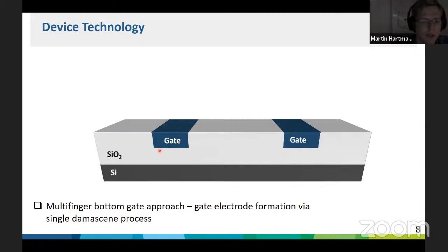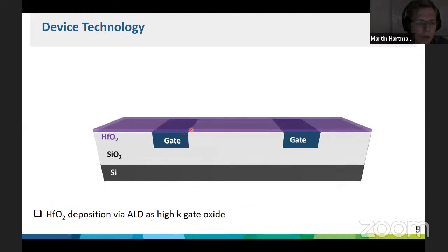So Damascene process means that at first we etch into the oxide some trenches, we fill it with metal, and then we polish away with chemical mechanical polishing until the trenches are filled and you have almost no dishing between the surface of silicon oxide and the gate. Then we deposit a high-K dielectric on top here. This is typically hafnium oxide.